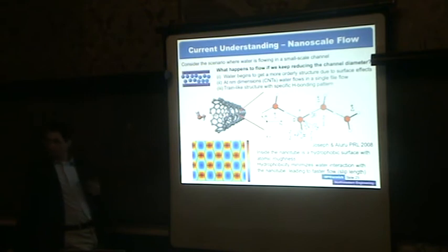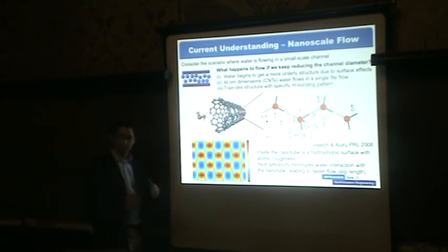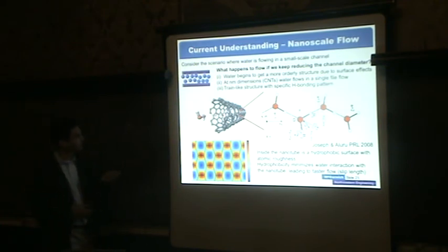So the water doesn't like the carbon nanotube surface. As a result of that, you have what we call sort of a slip-like flow behavior. So slip length is sort of a continuum description of how much friction you have in the channel. And in this case, you have much less friction than what would be a stronger chemical interaction with the water.